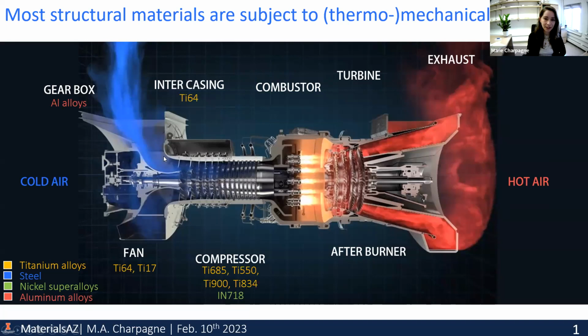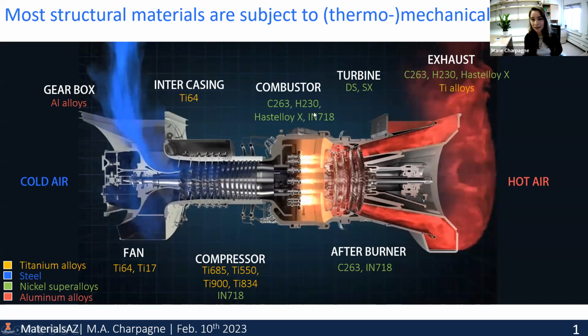And then as we increase in temperature, there are titanium alloys mostly. This is going to the compressor stage here, a variety of titanium grades. And then in the hottest parts, we have nickel-based superalloys, which can be polycrystalline, such as Inconel 718, that's very famous, or Hastelloy X, but also some single crystals or directionally solidified structures, which you can find in the hottest sections that most resist creep.